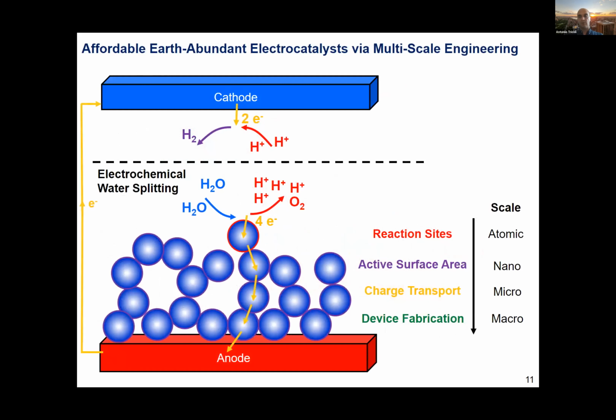The reason is that platinum and iridium are amazing materials. They are stable, they have very high surface activity, and they have very good electrical conductivity. However, when you start using something like iron oxide, the conductivity is not good. So you have to start engineering the structure all the way from the surface to the microscale so that you're able to control both surface activity, making it efficient to split water, and the transport of electrons, making sure you can do it at the high rate necessary to obtain industrial capacity and not lose too much in the process.